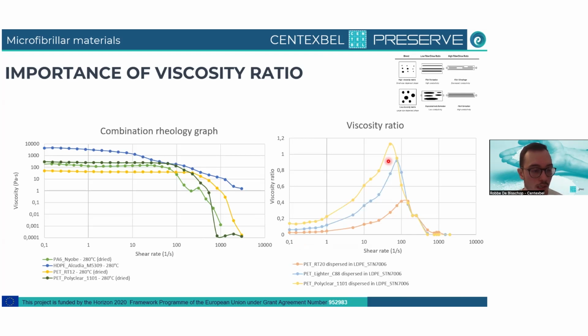I wanted to show you here as well different viscosities. So how much can a viscosity actually change when you use different materials? We have done this analysis with virgin materials. You can see the different grades here. And on the right, we look at the viscosity ratio, so the viscosity of your dispersed phase divided by the viscosity of your matrix phase.